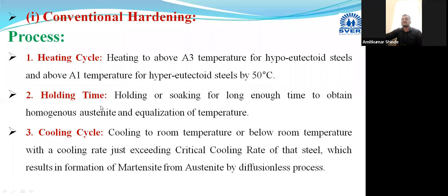Then we are holding that sample in this temperature zone for some definite period of time, depending on the shape and size of the component and composition of that steel. Okay, holding time. If that steel is a high carbon steel, or it consists of other alloying elements, or carbon percentage is very high, then the holding time required will be more. And if the shape and size is larger, or some complex shaped component is there, then the holding time automatically increases.